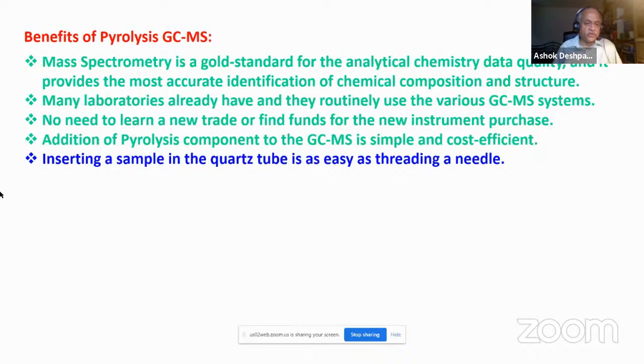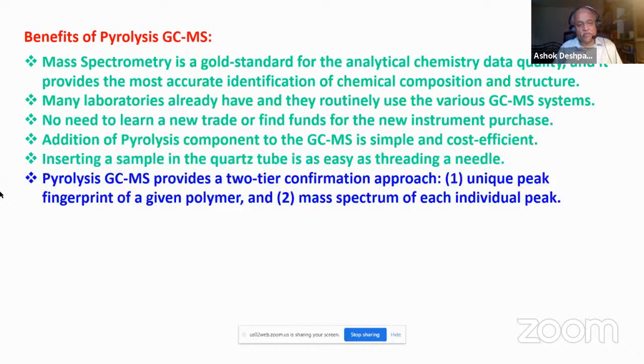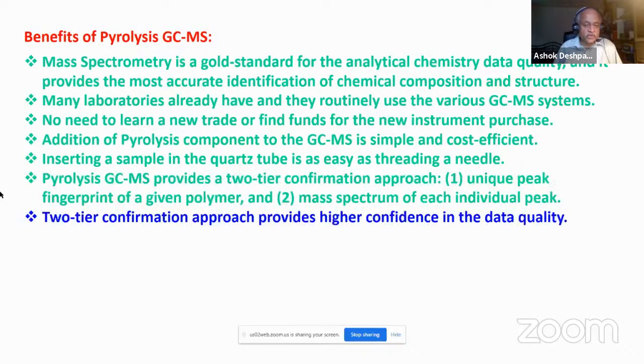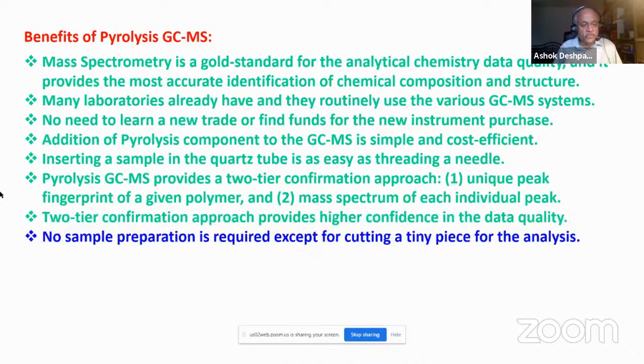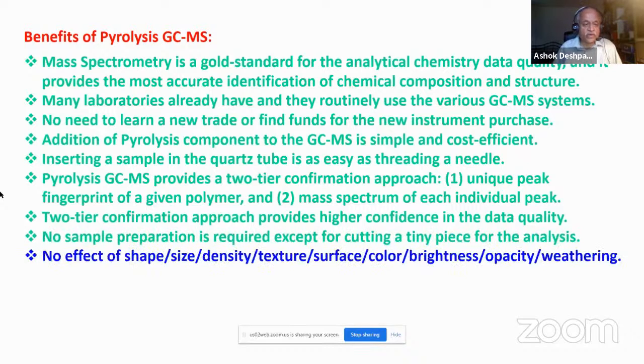Inserting a sample in the quartz tube is as easy as threading a needle. Pyrolysis GCMS provides a two-tier confirmation approach, unique peak fingerprints of a given polymer, and mass spectrum of each individual peak. The two-tier confirmation approach provides higher confidence in the data quality. No sample preparation is required except for cutting a tiny piece for analysis. There is no effect of shape, size, density, texture, surface, color, brightness, opacity, weathering, etc. on the data quality.